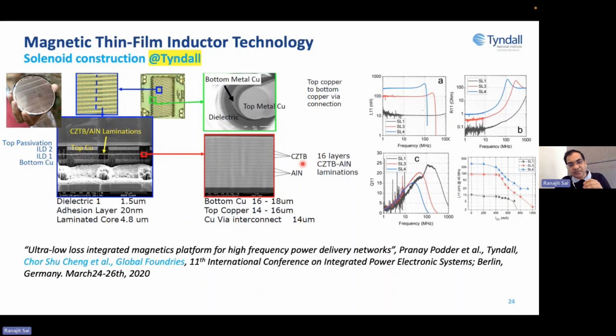Sorry. So those laminations are cobalt, zirconium, tantalum, boron based magnetic film layers, 16 of them. Each of them is about 250 nanometers thick, and in between two magnetic layers there is a separation of aluminum nitride, which is about 20 nanometers thick. Okay, so that's the structure.